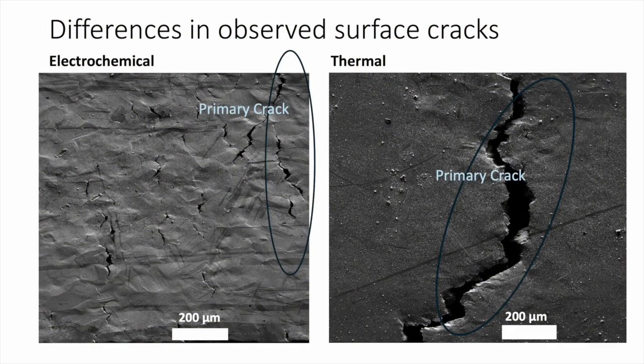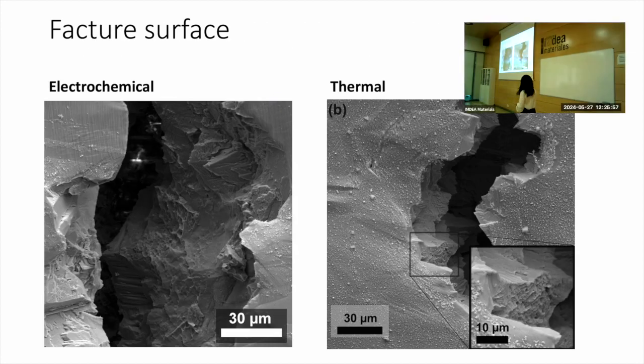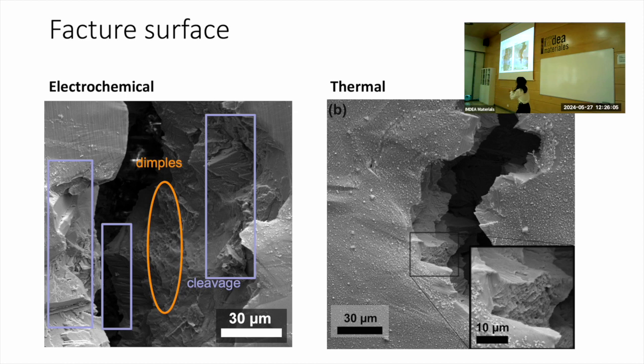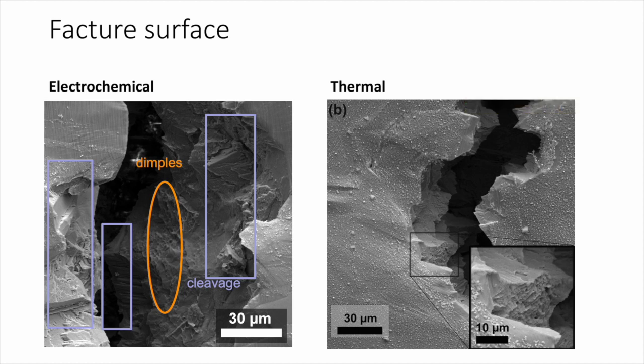If you look at our electrochemical charged sample, this is our primary crack, and all of these are secondary cracks. But in our thermal charged ones, we only have one primary crack, and we don't have many secondary cracks. If we look at the fracture surface, then we find that in the electrochemical charged one, we have the dimples in the middle and this cleavage at the surface. This also proves that the surface part is hydrogen embrittled, just as the hydrogen distribution we saw. And as for the thermal charged one, we have this combined cleavage and dimple sort of structure. So this makes us wonder, okay, there might be some difference between the crack initiation process in the electrochemical charged sample and the thermal charged sample.